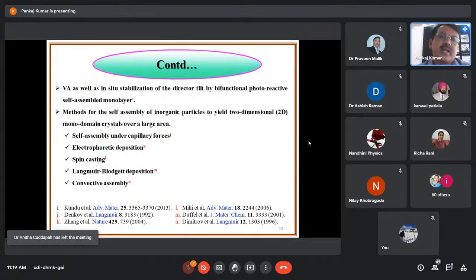So VA as well as in situ stabilization of the pretilt by bifunctional photoreactive self-assembled monolayers has been achieved by the authors. There are methods for the self-assembly of inorganic particles to yield a two-dimensional monodomain crystal over a large area. In that case, people have used different methods, that is self-assembly under capillary forces, electrophoretic deposition, spin coating, spin casting, Langmuir-Blodgett deposition, as well as convective assembly. So different authors have used different methods to make the self-assembly of nanoparticles for making the vertical alignment without any coating, without any sophisticated techniques.